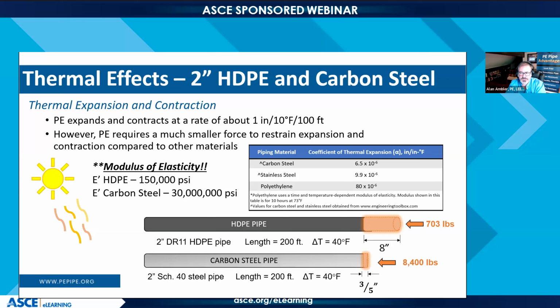So one thing that I've observed is that an accurate estimation of what could actually happen in the field, as far as the temperature change that the pipe might endure, is pretty important for what we're looking at. But one of the things that's unique about high-density polyethylene is it does have a lower modulus of elasticity than other pipe material types, and a higher coefficient of thermal expansion, which will allow it to change more. So in this example, we simply did 2-inch DR11 HDPE and 2-inch schedule 40 steel, 40 degree temperature change, 200 feet length. The HDPE would move 8 inches.